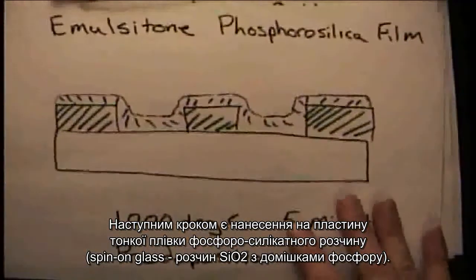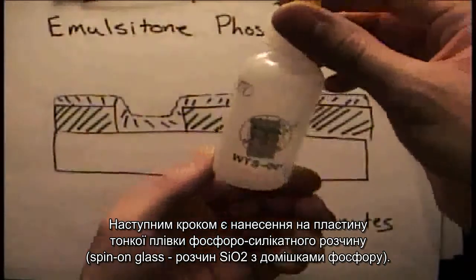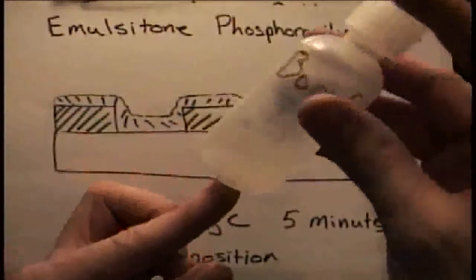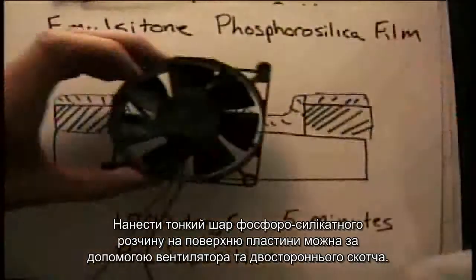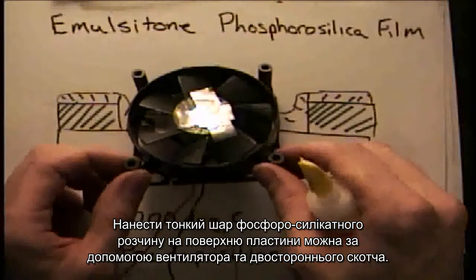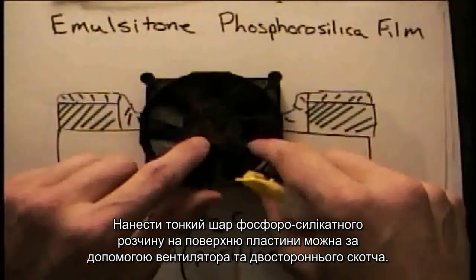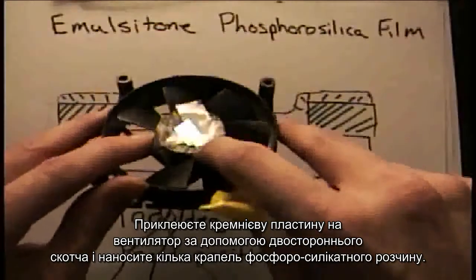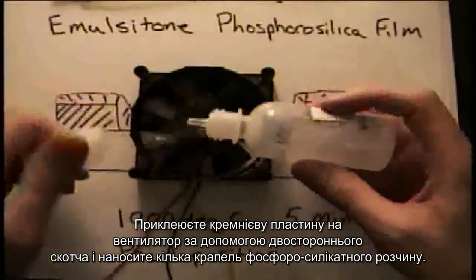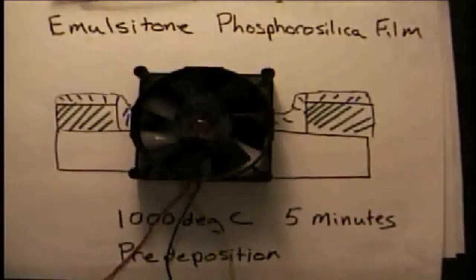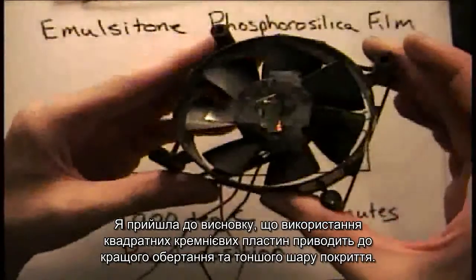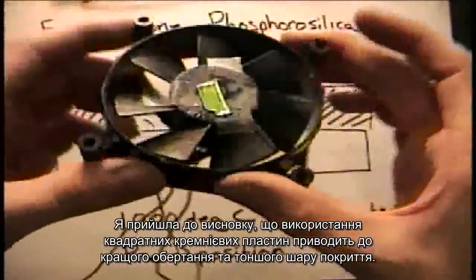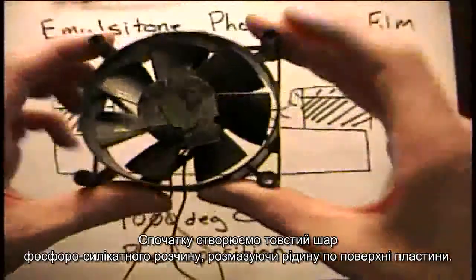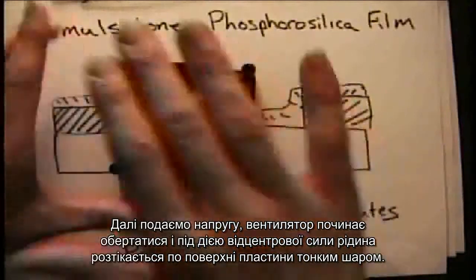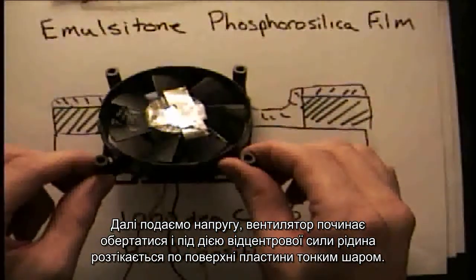The next step is we're going to spin the phosphosilicate film onto the wafer. It's a very thin fluid. You can spin it onto the wafer by using a CPU fan that has double stick tape on it, and you can stick the wafer piece onto the fan and apply this liquid. I found that if you're using square pieces of wafer, it's better to rock the wafer around and coat it, kind of a thick coating all around first, and then turn the power on and spin it, and it'll spin off the excess and make a very thin layer.